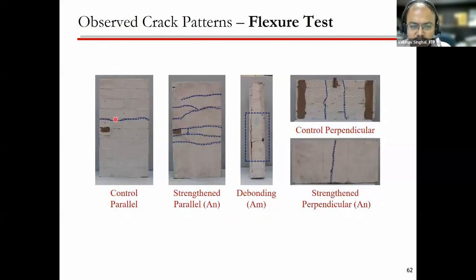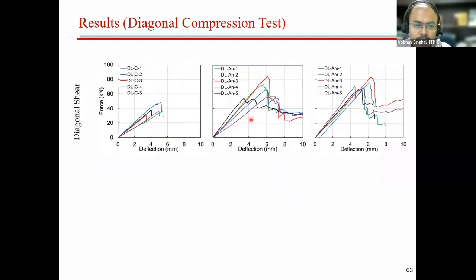These are some of the failure patterns which we have seen. In some cases, especially when the anchors were not used, we have seen debonding, which is not preferred. Even the adhesive mortar, of course, has good adhesive property, but debonding was commonly seen, especially without anchor. So it is suggested that some anchor should also be used when using this strengthening technique.